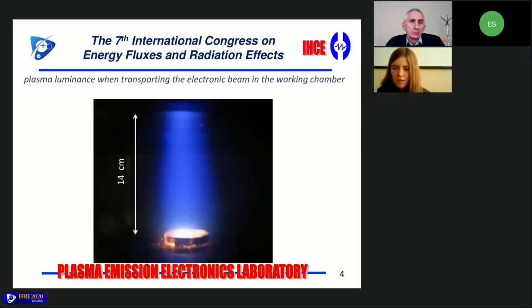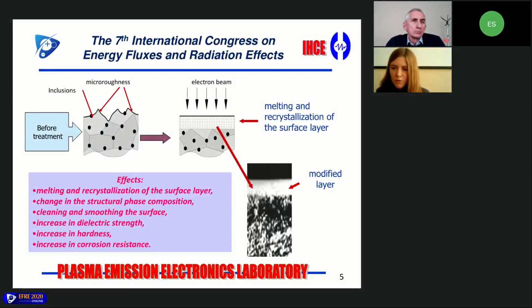Here you can see the appearance of the electron beam in the chamber. Before treatment, we have a rough surface with a big amount of different inclusions and micro roughness on the surface, but after our electron beam treatment, we have a melted and recrystallized surface layer. So we have a modified layer, which is smooth and with enhanced mechanical properties.